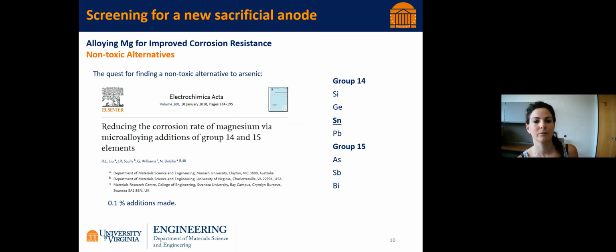characterized magnesium tin alloys after they'd been immersed in a salt solution. And they found that there were reduced hydrogen evolution rates. And this was put down to a tin-enriched surface layer that was accumulating at the interface between the passive film and the underlying alloy. And so this tin-rich layer was able to act as a surface for sluggish hydrogen evolution reaction kinetics, which coupled with the magnesium matrix and effectively replaced the sites for this strong hydrogen evolution reaction on the normal magnesium hydroxide corrosion product.